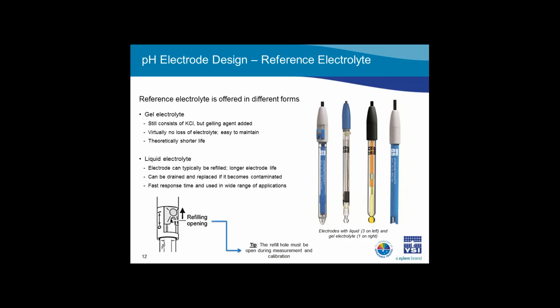Electrodes with liquid electrolyte can usually be refilled. This results in a longer electrode life. It also allows the user to easily refill the electrode when needed, as well as replace the electrolyte if it does become contaminated. Response time of the electrode is typically faster, and the measurement signal is more stable if liquid electrolyte is used. Faster electrolyte outflow from these electrodes also helps to reduce troublesome diffusion potentials that may develop, and it also ensures the electrode junction doesn't become easily clogged. If you were in the lab, I would definitely recommend an electrode with liquid electrolyte.